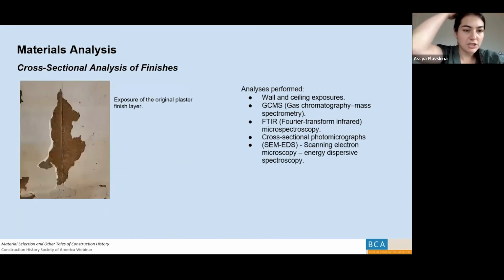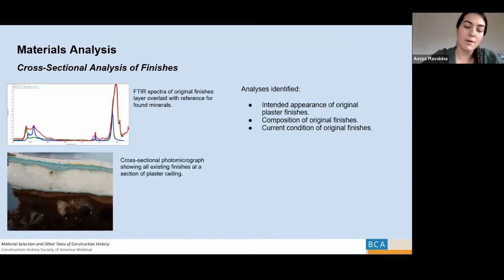We also performed some finishes analysis. What you see in that photograph is an exposure of the original plaster finish layer. This is actually one of the first things that we did when we got into the church, was do these exposures. And you can see that scored joint line there. This was actually probably the first time we found out that Trinity had this faux masonry finish, was during this exposure. It had been completely obscured through multiple layers of refinishing since. And the goal of our finishes analysis was to understand the composition and also try to understand what the intended appearance of that original finish was, and then to find a way whether it could be conserved or replaced with a similar finish.